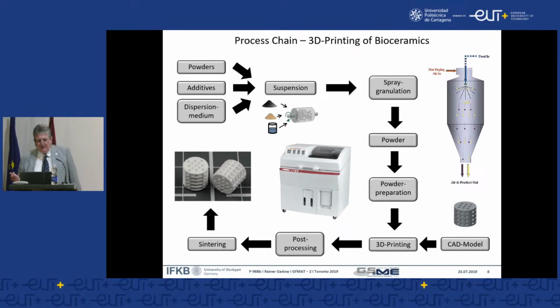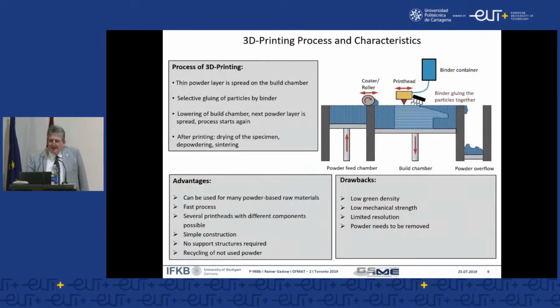And the component is made by the 3D printing. 3D printing is the forming process, but for a ceramic material, the forming is not enough. After the forming, we have to select the appropriate heat treating. That means the material must be sintered. And sintering for such a porous structure also means a shrinkage. And this must be overcompensated by the calculation in the CAD model. So the typical linear shrinking rate is 15 to 20%. Yeah? That means the sintered part is distinctly smaller than what we call the green part that is coming out from the machine. So today we have a broad variety of 3D printing machines, 3D printing processes.